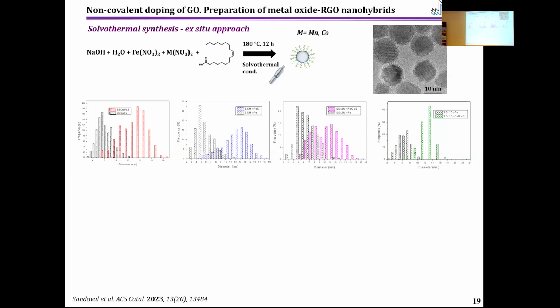So we can even prepare mixed magnetic nanoparticles. In this case, for example, I have done a two-step protocol in which I prepare 6 nanometer nanoparticles in all cases, and then prepare a core-shell which can be formed by the same crystal, I mean the same cobalt ferrite, but also we can change the counter ion, and we can prepare mixtures of different magnetic materials. So in this case, for example, we have a manganese nanoparticle covered by a shell of cobalt ferrite nanoparticles. So we can tune the magnetic properties of the particles before attaching them onto the graphene oxide.